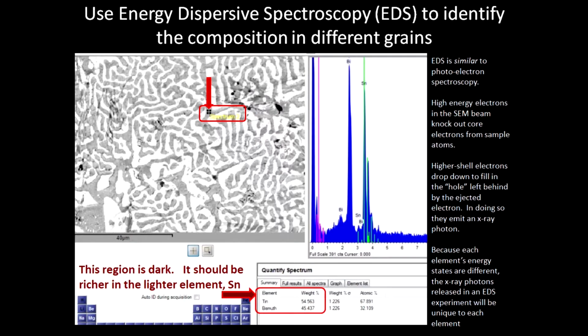But actually, we never really pursued it too far. And it turns out that the larger the nucleus, the lower the energy of the inner core electrons. And that jump to get down into that lower core is actually more energetic than visible. It's a little bit more energetic than beyond visible in the UV and into the X-ray region. So these regions, UV versus X-ray, there's not like a hard line defining the difference of them. And so sometimes they are UV photons that come out, but for the heavier elements, it's almost always an X-ray photon.